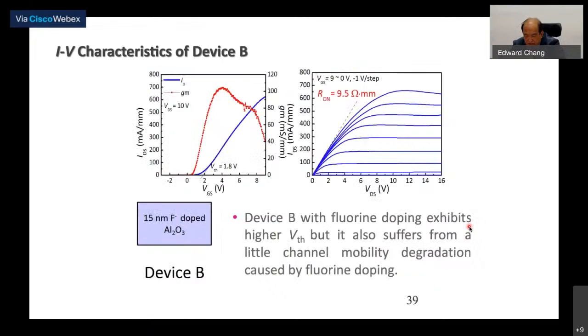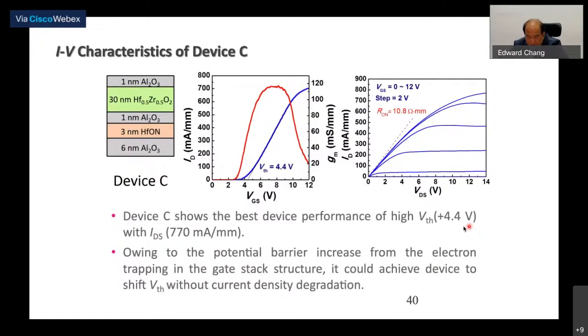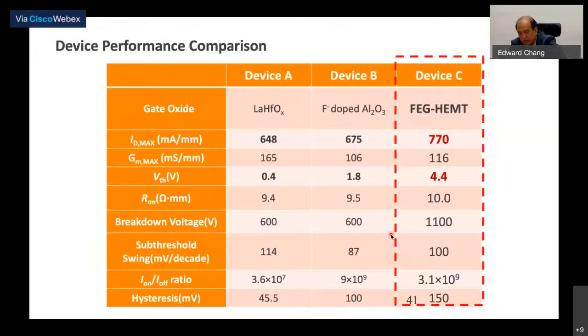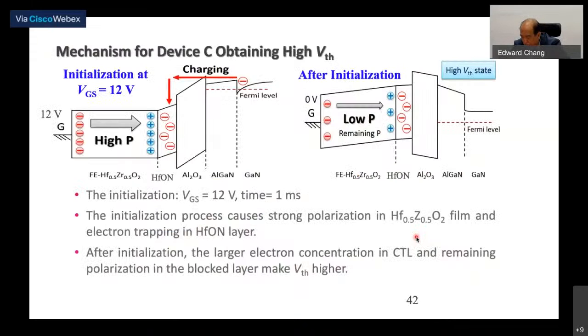The only one I'm going to present is ferroelectric oxide. It gives a very high VTH of 4.4 volt and a very high current of 770 milliamp per millimeter. If you compare to the other technologies we also fabricated, you can see that the ferroelectric FEG-HEMT gives you 770 milliamp per millimeter, which is very high. VTH is 4.4 volt and Ron is around 10 ohm per millimeter. Breakdown voltage is 1100, subthreshold swing is 100, and hysteresis is more. That's the feature of the device.